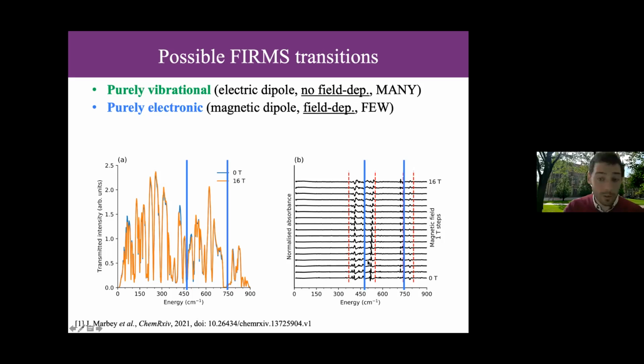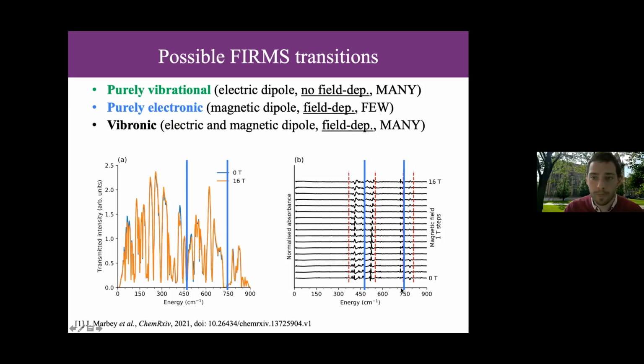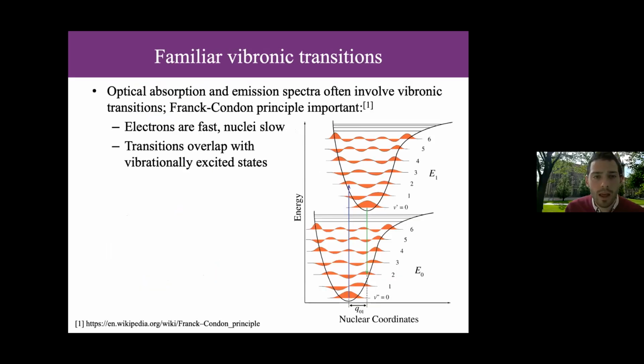Okay, and so we should see these, but there are only few of those, because we only have 4 Kramers doublets. And so we're only going to have a certain number of transitions in these energy ranges. And these, we know from the luminescence spectra. We know where these occur, and that's where these blue lines are. And then finally, we should have vibronic transitions. And these are going to occur at many different places and have a field dependence. And so just a quick interlude here.